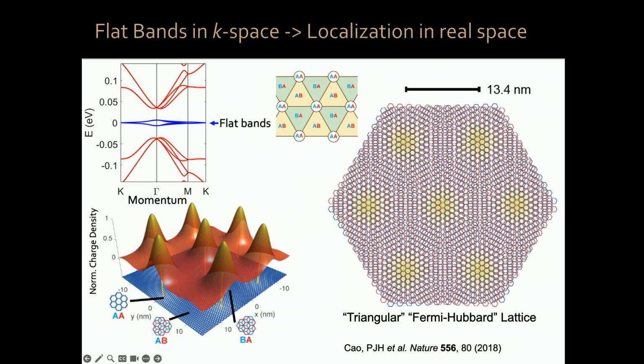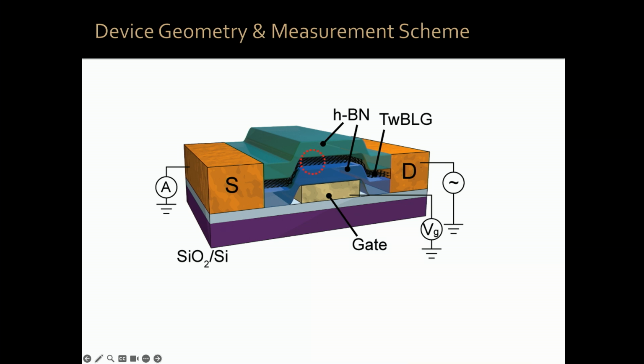Okay. Now, we make our devices, and we have a structure where we have the magic angle twisted bilayer graphene. This is encapsulated between two flakes of hexagonal boron nitride, hBN, which is just a material that makes sure our magic angle graphene stays very pristine, okay? And its electronic properties can be measured very nicely. We contact them with source and drain contacts. So if we apply a voltage, we can measure a current circulating through this thing.